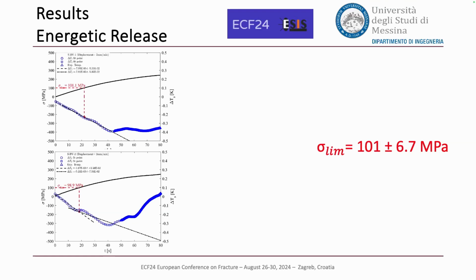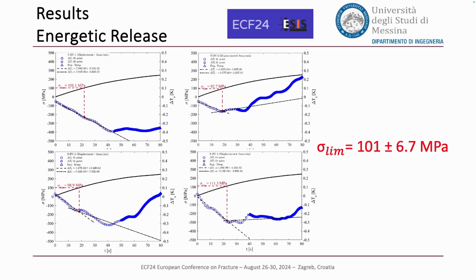So from the stepwise fatigue test and the constant amplitude fatigue test, we realized that the fatigue limit of the material aligns precisely with that phenomenon that we were not able to interpret in the static thermographic method. And we also have done other static tests to confirm this interpretation.